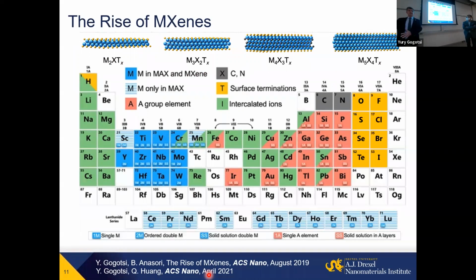We greatly improved scalability over the past year. We decreased the amount of water used from 150 liters to about 5 liters for 100 grams. Oh, sorry, for a kilogram of MXene. But issues still remain with MAX phases. We're looking, for example, at SHS synthesis.